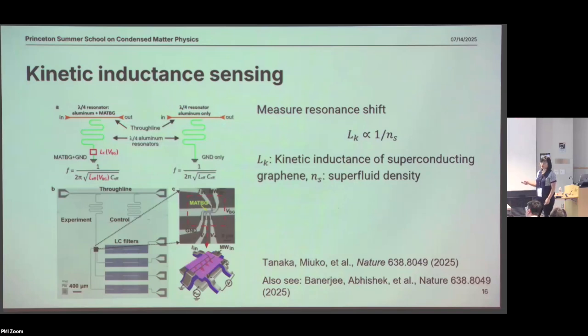So you have a lambda/4 resonator, an on-chip aluminum-based resonator that has a very high quality factor. A high quality factor just means that your sensitivity is high, or to say your electric field is really enhanced at its resonance. Its resonance is characterized by 1/2π√(LC), where L is the effective inductance of this resonator and C is the effective capacitance. But then what they did was put this material on to be a part of the resonator. So they connected the resonator by this material. It's a type of inductive coupling.